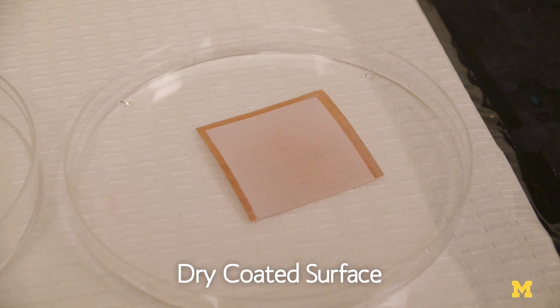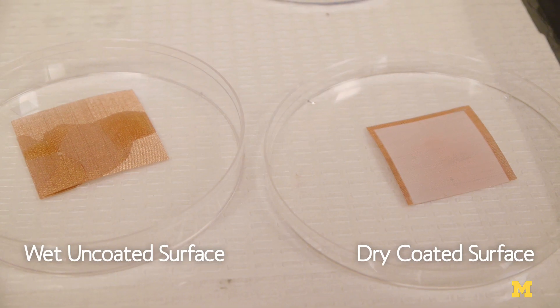The liquid actually starts to sit on millions of pockets of air, and I would imagine on the order of 95 to 99% of the liquid is actually just touching air. It's only touching 1 to 5% of the surface, and that has to do with the right surface texturing that we impart on the coating.